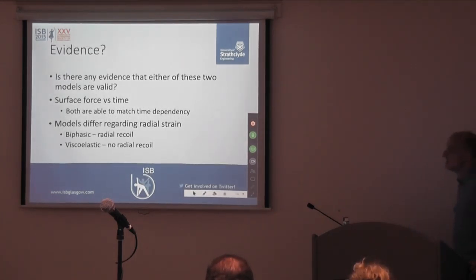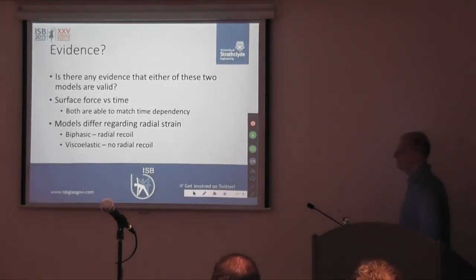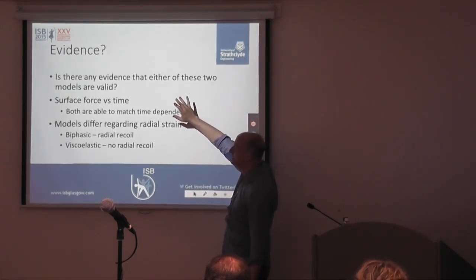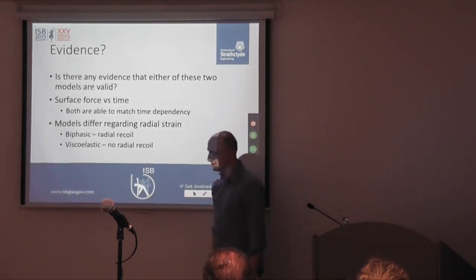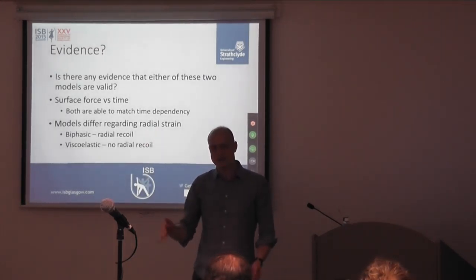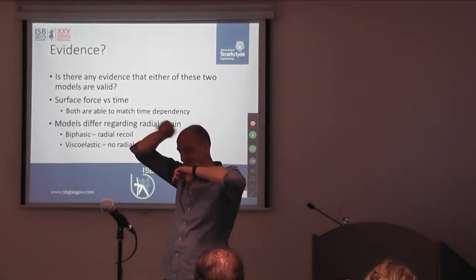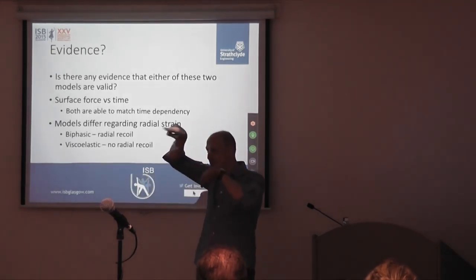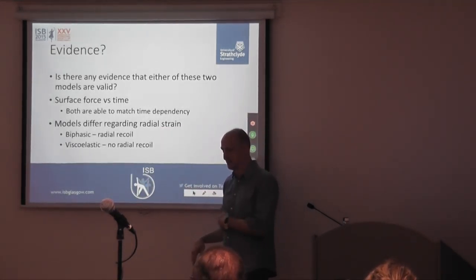Again, I'm asking, is there any evidence for this? Both models can predict surface force, but is there any evidence for the biphasic model having radial recoil? Now, this is a really tricky experiment to do because you want to compress something with zero friction. It's that zero friction coefficient on the top and bottom which is really important to try and get experimentally.